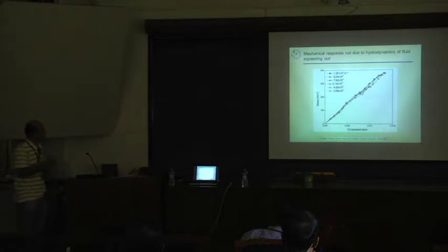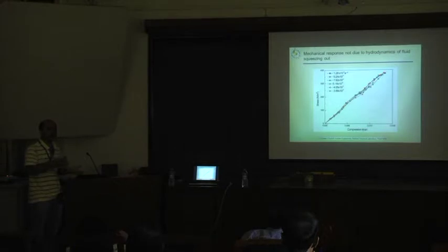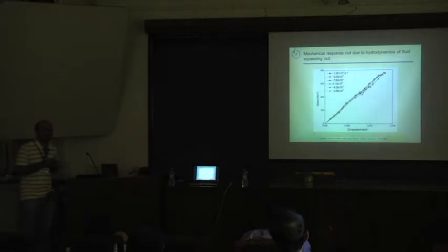So the first thing we looked at is whether hydrodynamics of the fluid squeezing out matters. You remember in the experiment that I showed you, the pores were filled with water. So we varied the rate at which you squeeze this out by over an order of magnitude, and there's no real change in modulus, suggesting that it's not really the pressure to force this liquid out that gives rise to the modulus.